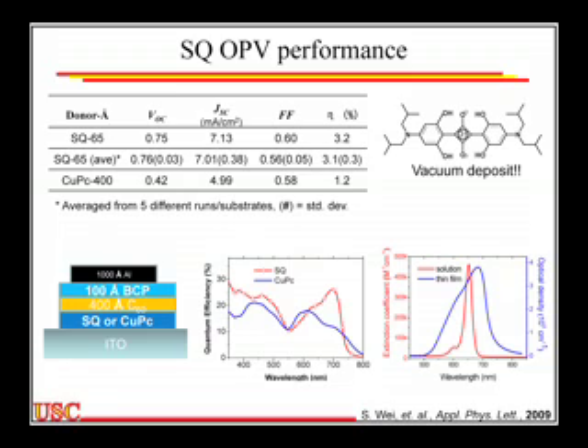It turns out the exciton diffusion length here is about 60 angstroms. We've measured this by luminescence measurements. And so you can see as she makes the film thicker, there's not a real gain. In fact, the current starts dropping. So that's 65 angstroms. Let me go down. This is 110 angstroms, 150, 200. The current is dropping because as she puts more and more squaraine in, we're radiating from the bottom, and it's actually attenuating the light before it gets into that last region between the C60 interface and the absorption window. So we can't make it much thicker than this, although I'll show you in a minute we can actually.